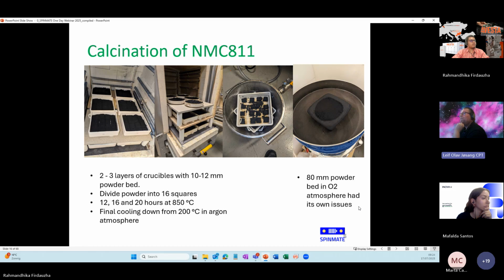Calcination. This is probably where most of the lithium disappears. And in the beginning, I used bigger crucibles because we were having in mind that we wanted to make maybe as much as 20 to 40 kilos of the material, and bigger crucibles would be better. The challenge was that in order to get good structure of the material, we needed to go so high in temperature that we ended up with a lump that you can see on top of a sieve towards the right, at the right-hand side here. So when you want to make a cathode layer, a particle size of 10 by 10 by 5 millimeters is a bit on the coarse side.